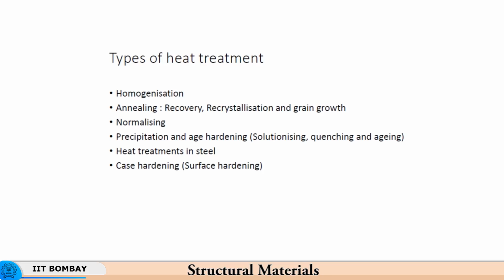We will see how we can harden the surface selectively, but then having hardened it selectively, the deformation of the surface subjected to large bending stresses, not strains, large bending stresses, you will have very small strains being created, because now the material is stronger at the surface. So, naturally the strains created will be that much smaller, and therefore, the kind of damage it will accumulate will be that much lower. So, that is why we have case hardening or surface hardening type of treatments which are available for different materials.